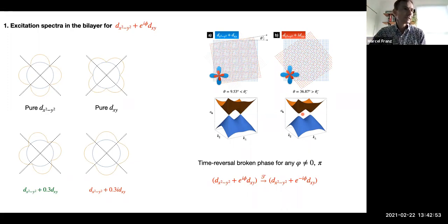It has a Fermi surface, but then as electrons condense into a superconducting state, a gap opens up around the Fermi surface, and there is no gapless excitation. So, for instance, a superconductor cannot absorb any light with frequencies below the gap. That's been very well established.